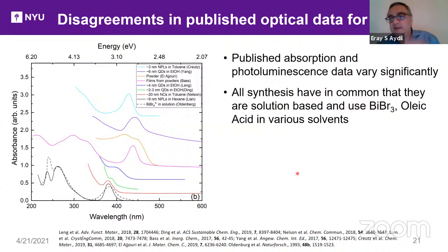So the first thing, I wanna take a little detour. When you're looking at a material that hasn't been studied too much, as opposed to something like cesium lead chlorides and bromides, there are some roadblocks that you enter. For example, published absorption and photoluminescence data varies significantly in this particular material, Cs3Bi2Br9, trigonal system. All approaches have used solution-based methods, and they all have in common that they use bismuth bromide and oleic acid in various solvents.